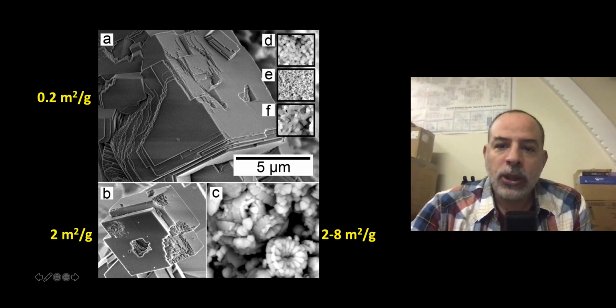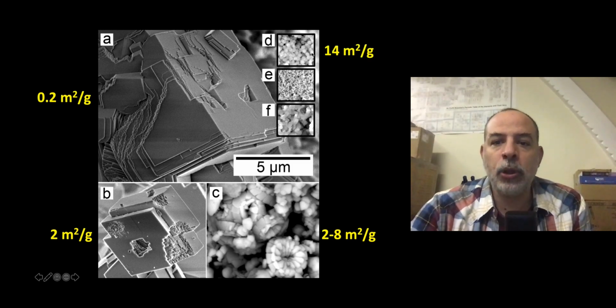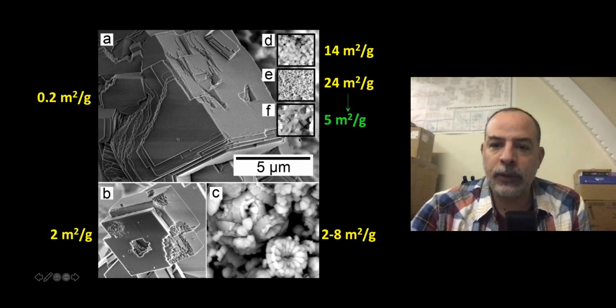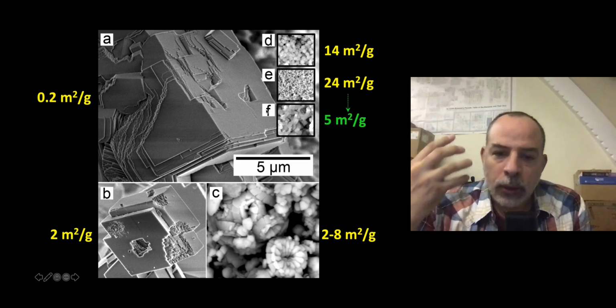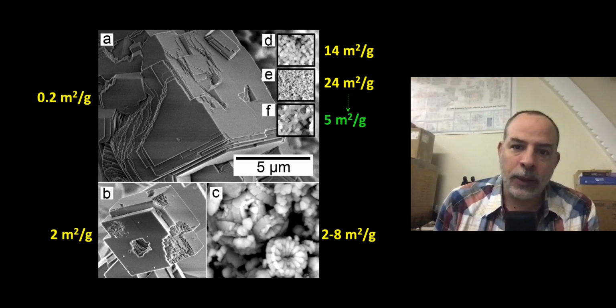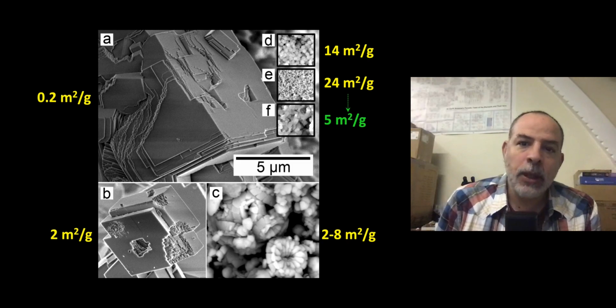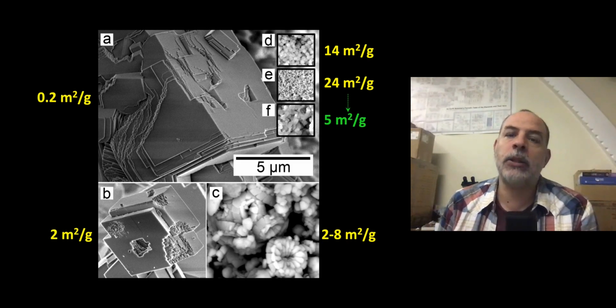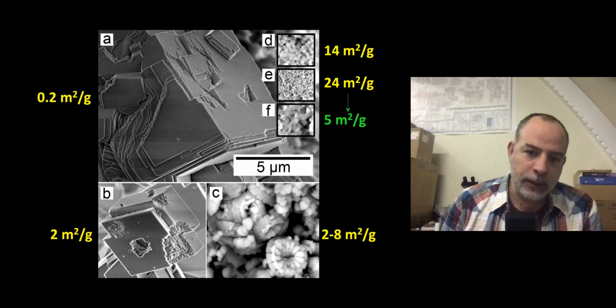And here what you see is our 3 nanocalcites. So this is the smaller surface area of spherical nanocalcite. This is the larger surface area of our nanocalcite, and this is what you get after the interaction of this nanocalcite with water. Okay, so you can compare the sizes here because the scale bar is the same for all of them. So this shows you how important it is to control the mechanisms of nucleation and growth, and to understand what is happening in our system to be able to obtain calcite with the properties that we want, with the surface area in this case that we want.